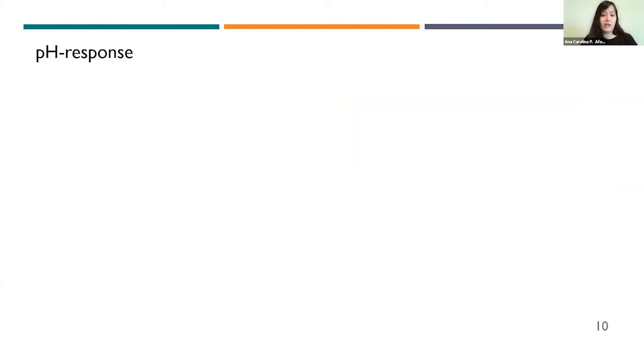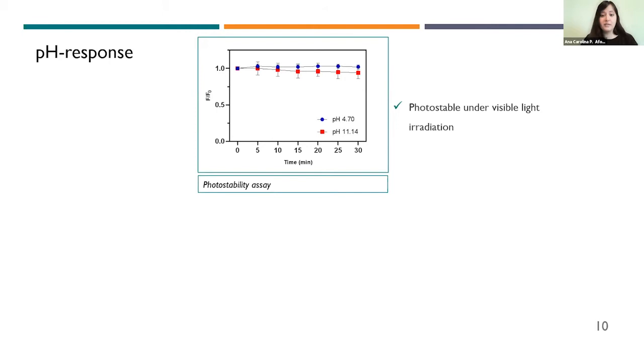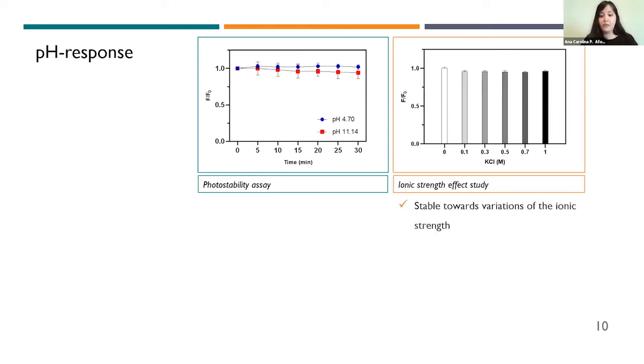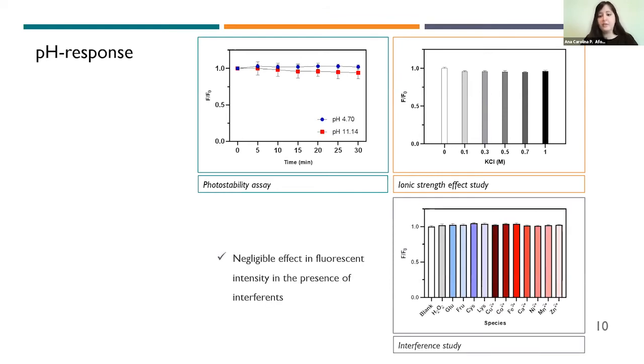As pH sensors require good stability and selectivity, we performed an array of tests, starting with a photostability assay of the carbon dot in acidic and basic pH, where it showed itself to be photostable under visible light irradiation. The effect of the ionic strength on its fluorescence intensity was also evaluated by preparing a series of solutions with different ionic strengths, and the increase of potassium chloride showed no appreciable effect on the signal intensity of the carbon dot. We also investigated the potential interference of different species toward the fluorescence signal of the carbon dot in aqueous solution, where no relevant change was seen in the presence of either interference.